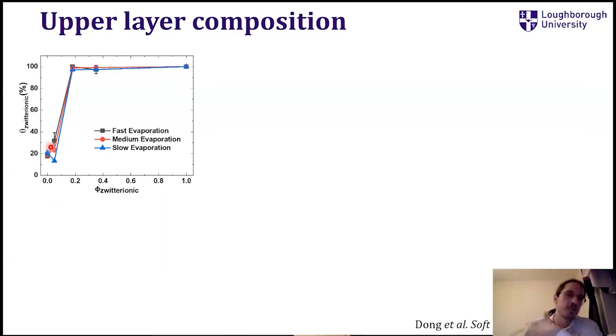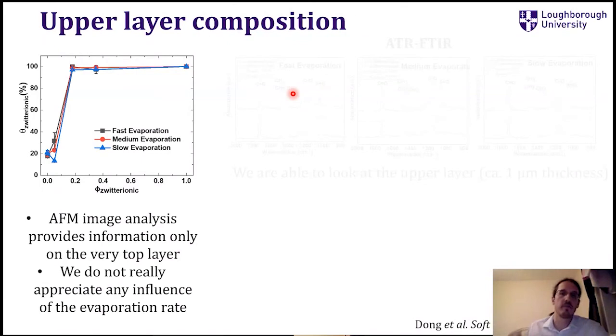But in this case with AFM, we just see that it increases to a plateau to 100% and that's it. So we are just looking at the very, very top. So we said, okay, should we look at a bit thicker layer to see how evaporation rate might affect, because here it looks like it's not changing anything. So for that, we use FTIR, so infrared spectroscopy.